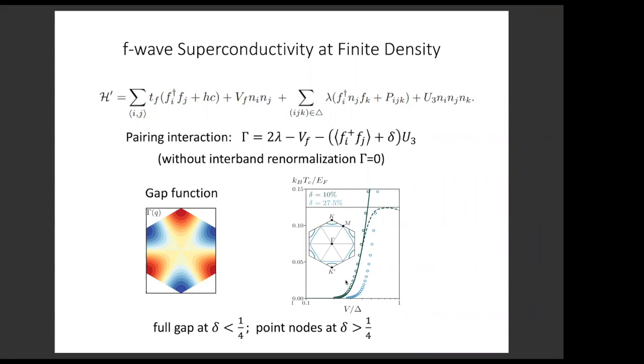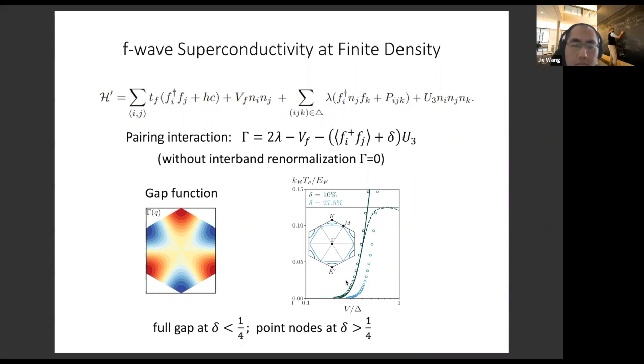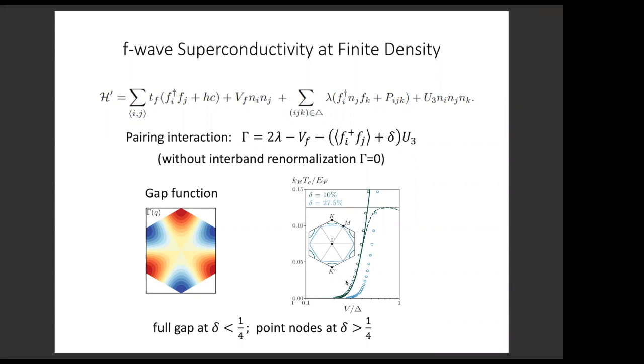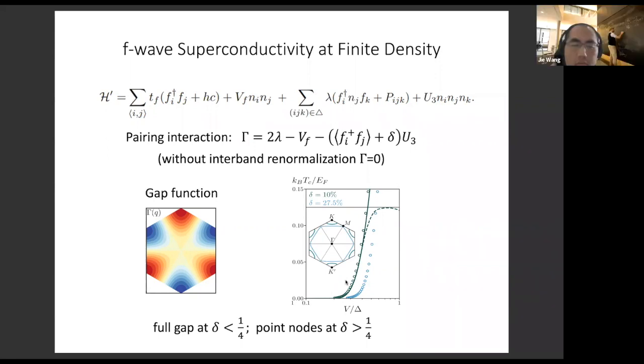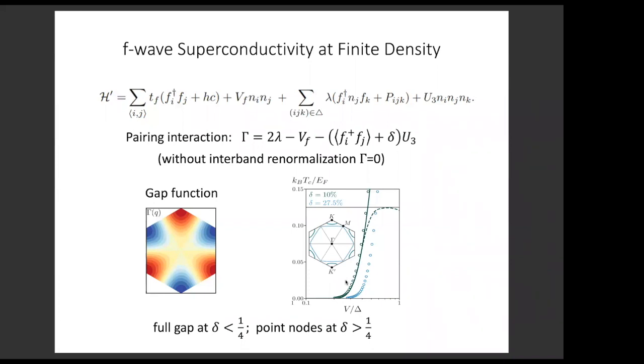So one thing I want to emphasize again is that if we directly do a projection of the original pair interaction without taking into account interband processes, then the pairing interaction in the F-wave channel is exactly 0. So this again says interband renormalization is crucial for pairing. Here we also show the TC as a function of the interaction strength V, and you see that TC will reach all the way up to about 10% of the Fermi energy as we increase the interaction strength.